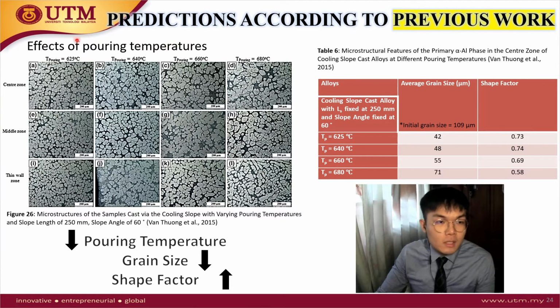And this is the previous work studying the effect of pouring temperatures. When using a low pouring temperature, we obtain a smaller grain size and a higher shape factor. These microstructure images are summarized and quantified in this table. Note that the initial grain size is from the conventionally cast sample without cooling slope casting. After cooling slope casting, the percentage reduction will be used to predict our cooling slope casting of AZ91D magnesium alloy. The shape factor is assumed to be the same because both alloys initially share the same microstructure.